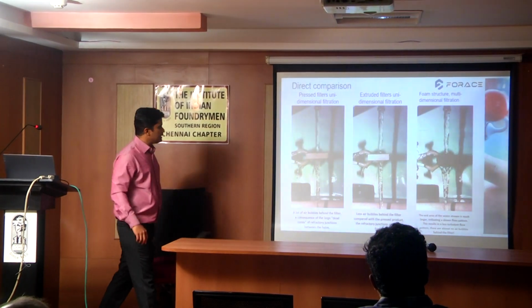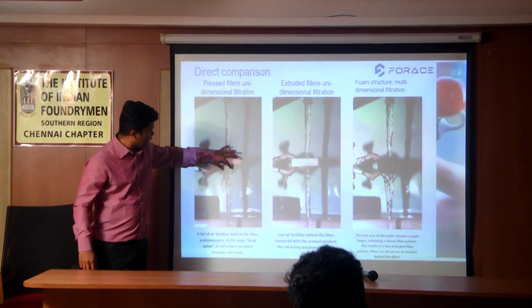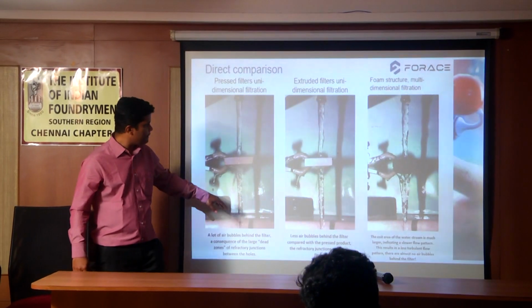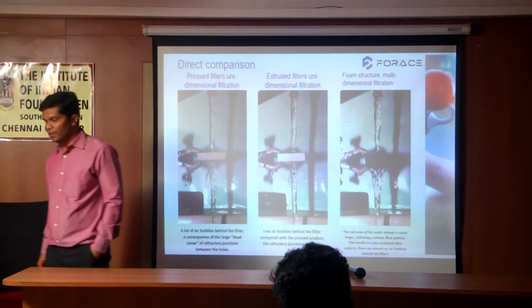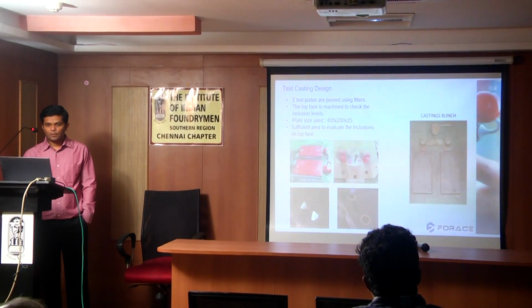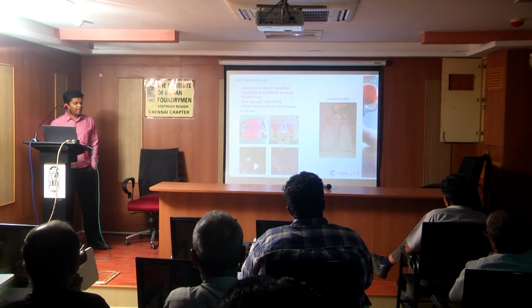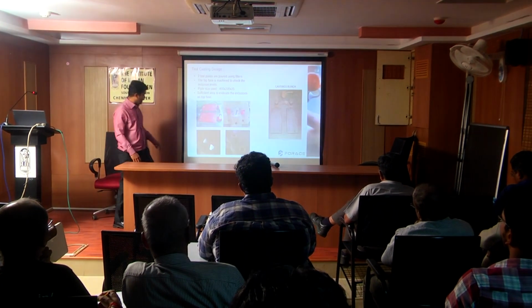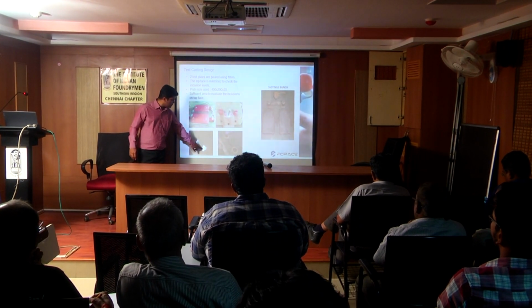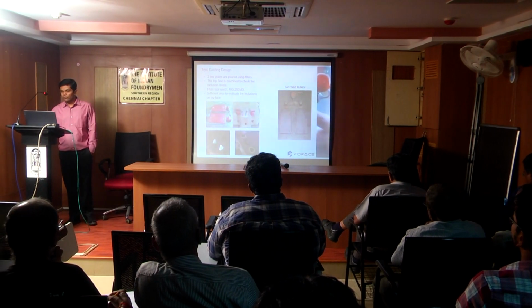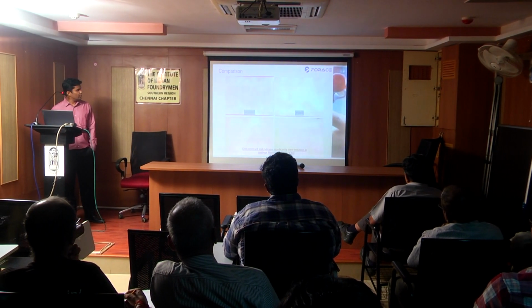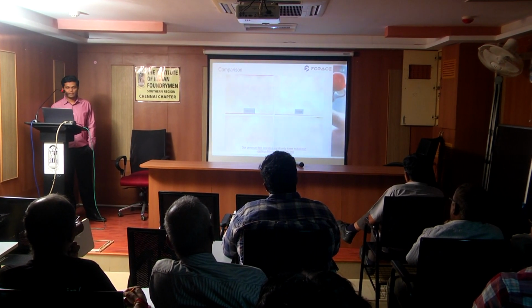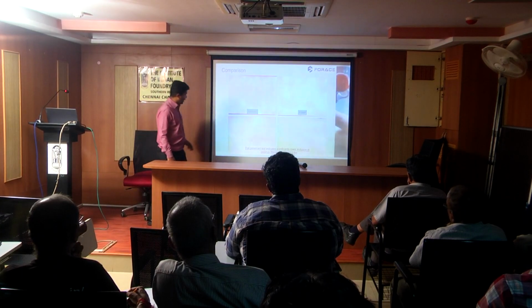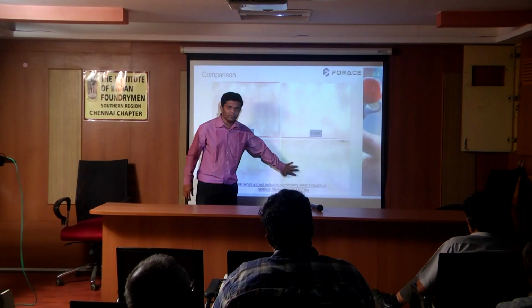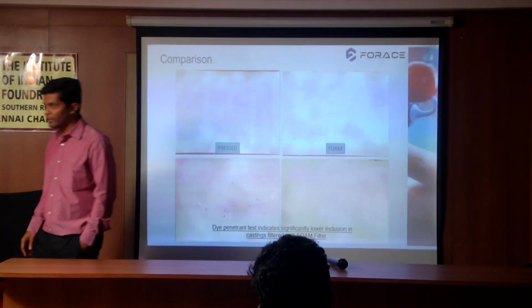So you can also check the flow. If you say this is the diameter, then almost an equal diameter is coming out, but with the foam filter you can see almost a converging type of flow. You can say the foam filter is using the full area of the filter. To prove this, we did a plate test. In one cavity we kept a foam filter and in another an extruded or press filter. We poured it, then machined it, and did a dye penetration test. In that you can clearly see that, as compared to the press filter, in the foam filter the particles or inclusion levels are very low.